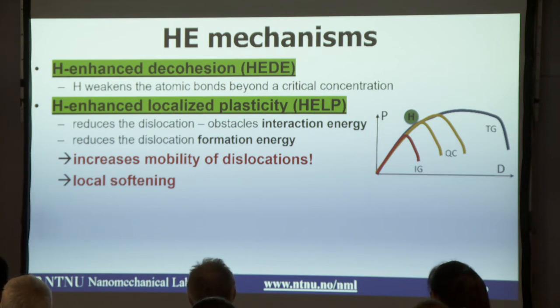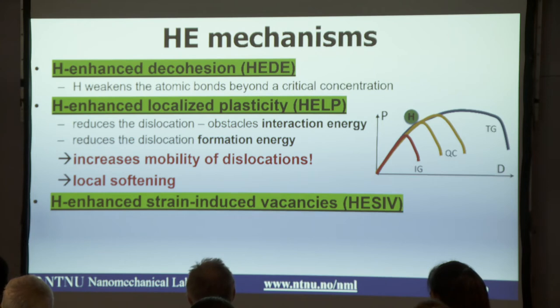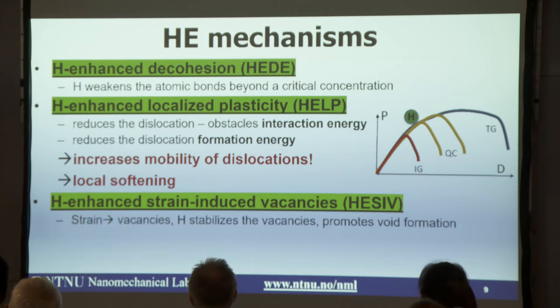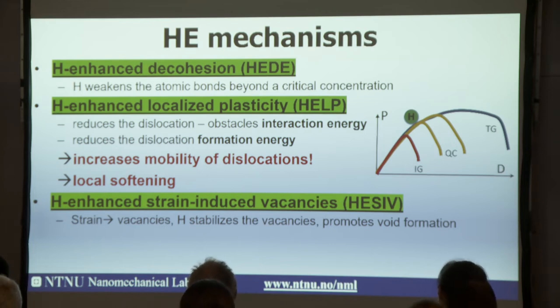The third one I would like to introduce is a relatively recent one proposed by our Japanese colleagues. That's called hydrogen enhanced strain-induced vacancies. You know, plastic strain will induce vacancies. These vacancies are not necessarily stable. However, if you charge the material with hydrogen, these vacancies become stable. These vacancies will promote the formation of voids.